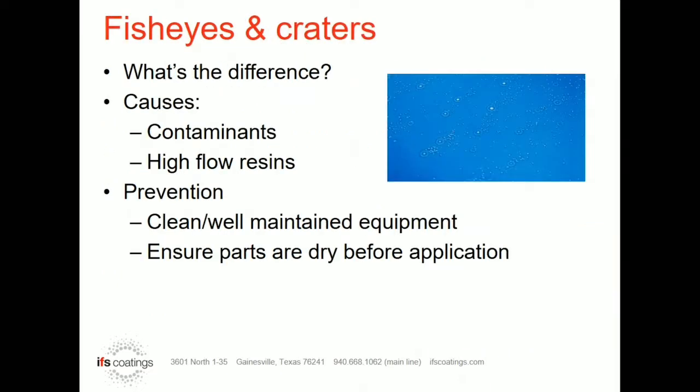Yeah, and I think to that last little note there, just because you blast something or mechanically remove some of that surface doesn't mean that it won't outgas. To outgas, you have to bring that part above your curing temperature. You might need to blast as well, but to outgas, it is getting the part up to temperature so that reaction occurs before you get a coating on it.